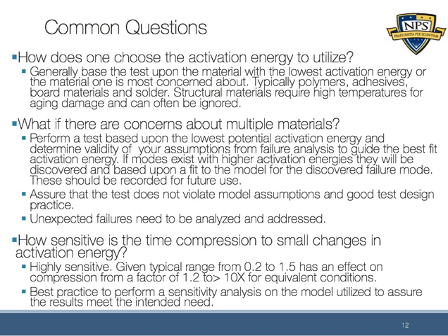And so, it's one of those times where you almost want to convince yourself, force yourself to choose the lowest possible activation energy, and then force yourself to be convinced to choose a higher one. And I'm not usually a fan of choosing the most extremes to make it look the worst, but in this case, because it's a sensitive variable, you could end up in a situation where your math was pretty far off if you chose a middle of the range value and it ended up being a low value. So that's just something to be careful of.